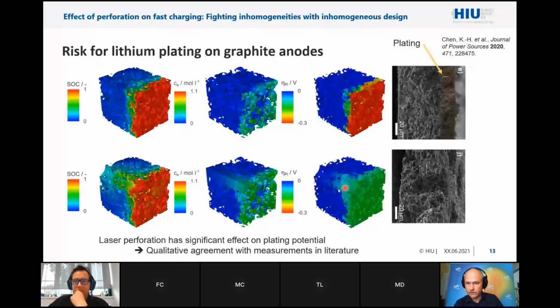You find plating, as we find in our simulation. If we are drilling holes into our virtual electrodes, we see that there is no plating anymore at the separator, and the same is found also in experiments. So one lesson is you might be able to accept inhomogeneities under operation, but then you have to do something in the design, namely trying to choose the proper inhomogeneous design to fight the inhomogeneity due to the operation conditions.